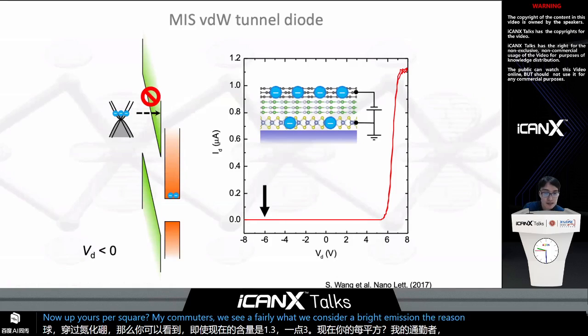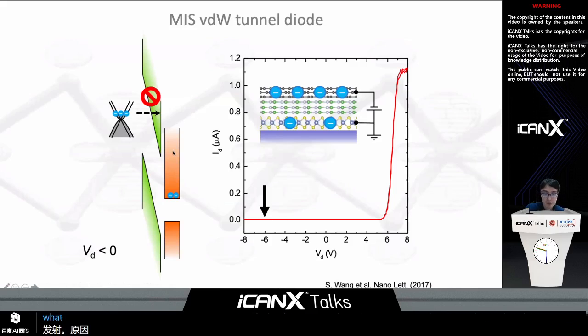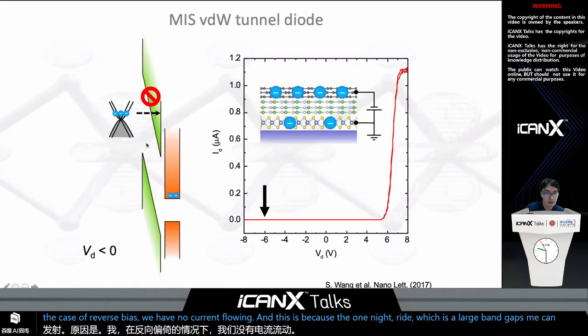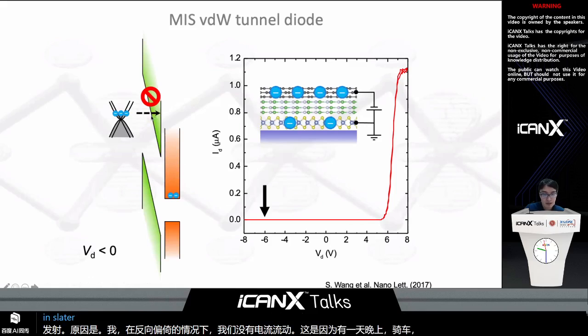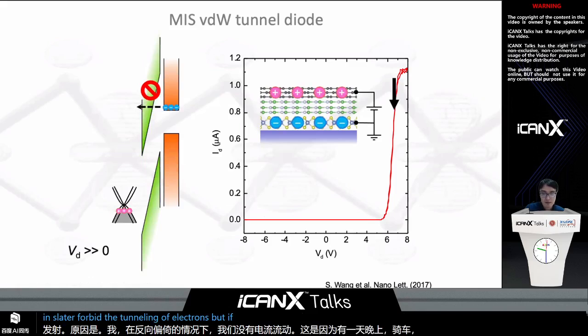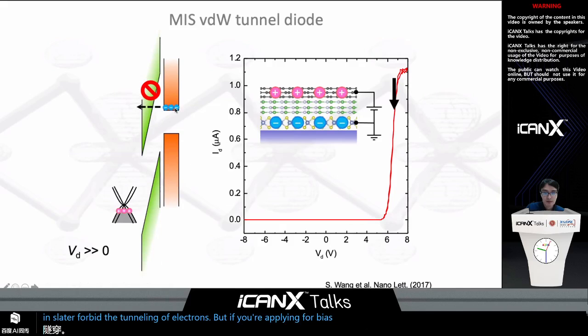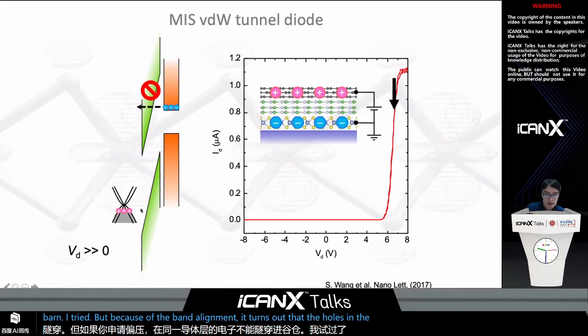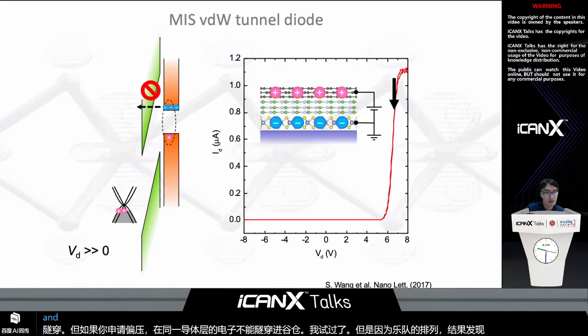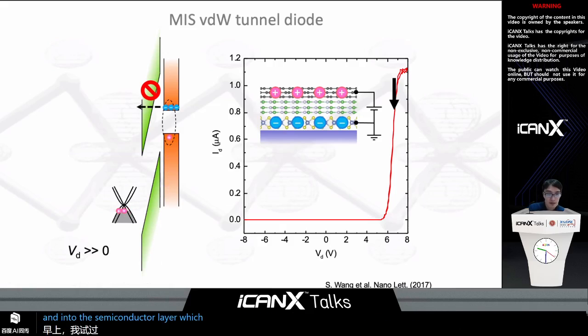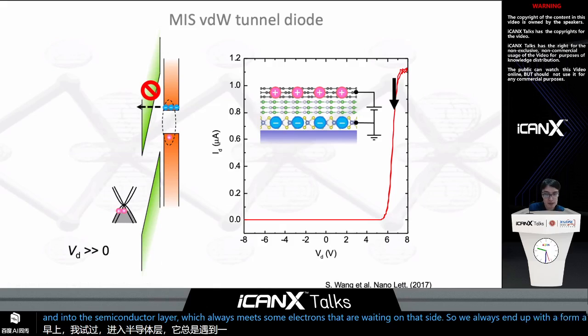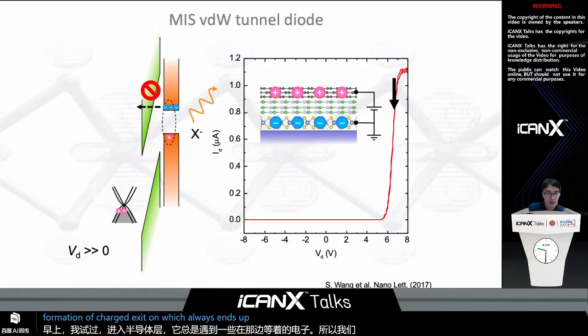The reason this works is because, in the case of reverse bias, we have no current flowing. This is because the boron nitride, which is a large bandgap semiconductor insulator, forbids the tunneling of electrons. But if you apply forward bias, the electrons in the semiconductor layer cannot tunnel into boron nitride. But because of the band alignment, it turns out that the holes in the graphene layer can tunnel into the boron nitride and into the semiconductor layer, which always meets some electrons that are waiting on that side. So we always end up with formation of a charged exciton, which always ends up emitting light.